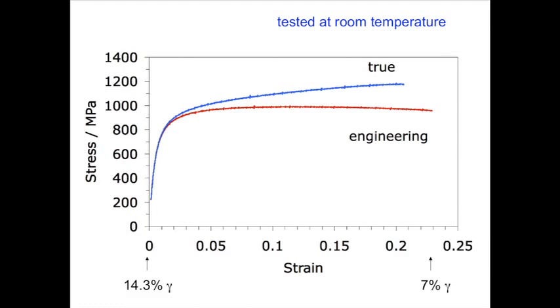Uniform elongation is what matters, not what happens after plastic instability. And if I measure the retained austenite content at the beginning, it's the correct amount, 15% I mentioned earlier. And as a consequence of deformation, some of that transforms into martensite, and that leads to work hardening, which you can see here.